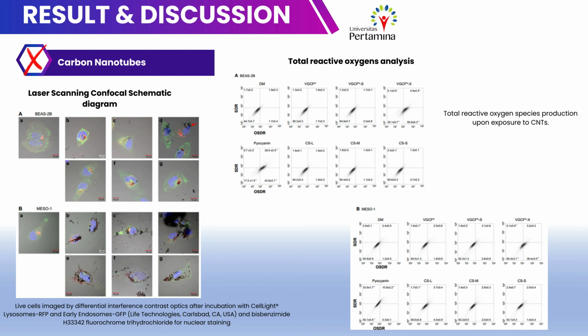The reactive oxygen species assay was used to measure the total amount of ROS and superoxide produced by the cell after exposure to CNT. The result of the ROS assay shows that total ROS production increased after exposure to carbon nanotubes, such as MWCNTs and GCNTs, in BEAS-2B and MSTO-211H cells. Exposure to carbon nanotube also increases the level of oxidative stress and superoxide dismutase activity in the cell.